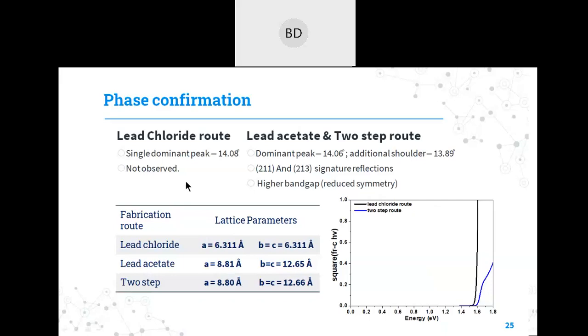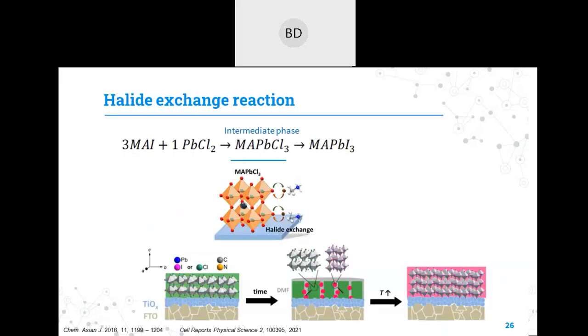So with all these observations, we came to know very confidently that there is a difference in the perovskite structure crystallization. And we speculated that this can be some reason for having different degradation processes in the perovskite films. Now the question is why this first route, the lead chloride route, is going for a cubic phase, whereas the other two routes are going for the tetragonal phase.